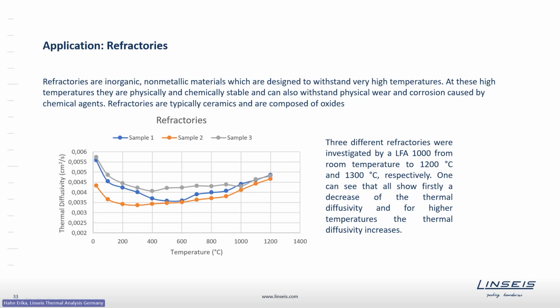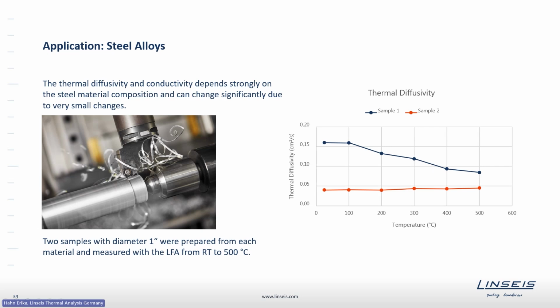So on the one hand, we had the graphite. Here we have, let's say, ceramic-based materials. The system can also measure metallic materials or, for example, polymers. Here we have an example for some steel alloys with 2 different degrees of alloying, and we can see a significant difference in behavior of both materials, just strengthening the point that the investigation of material properties is very important to know how the materials behave, especially at higher temperatures, as this can be very different from material to material.